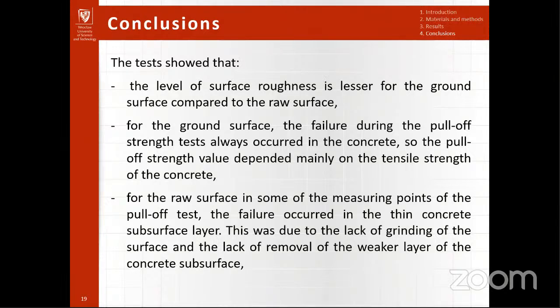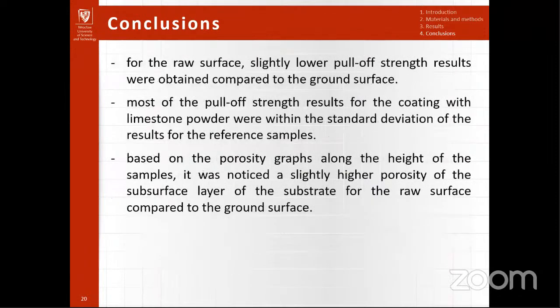For the raw surface, in some of the measuring points of the pull-off test, the failure occurred in the thin concrete subsurface layer. This was due to the lack of grinding of the surface and the lack of removal of weaker layer of the concrete subsurface. For the raw surface, slightly lower pull-off strength results were obtained compared to the ground surface.